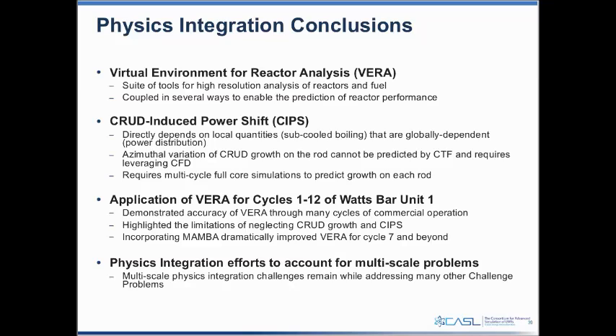The crud-induced power shift directly depends on many of these local quantities, subcooled boiling, for instance. But these quantities are very globally dependent, such as the power distribution. So they have to be modeled both at a very fine local level, as well as the full reactor multi-cycle distribution. So we have to account for this azimuthal variation of the crud growth in the rods, even though CTF can't predict it. And so that means we have to work with CFD to do that. And we have to be able to model many cycles of this as it grows on the fuel.